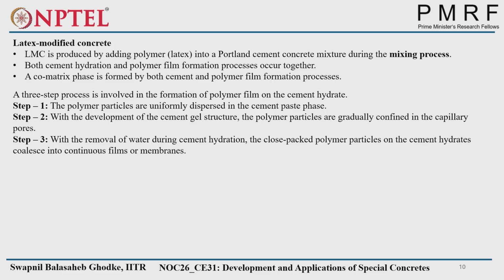Three-step process will be there. The first step, the polymer particles are uniformly dispersed into the cement paste phase, initially into the mixing phase. Step two, with the development of the cement gel structure, that is CSH gel, the polymer particles are gradually confined in the capillary pores. So whatever the capillary pores available after the gel formation, the polymer particles will get into that. Step 3, with the removal of water during cement hydration, the close packed polymer particles on the cement hydrates coalesce into continuous films or membranes. While the further cement hydration process uses that water, these polymer particles will surround the cement particles or the aggregate particles.